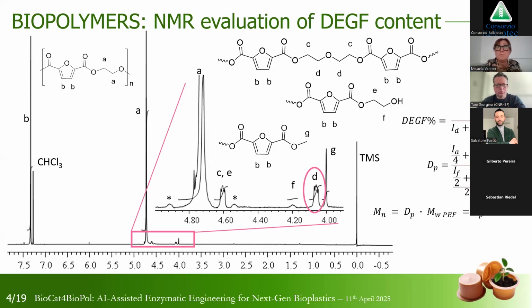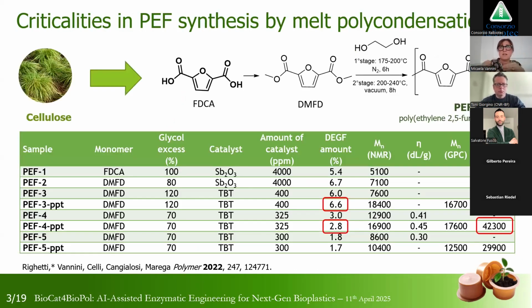For example, in the PET world, the presence of DEG lowers the melting temperature and glass transition temperature, slows down crystallization, and makes the polymer less thermally stable. So it's crucial to evaluate, but also to limit, the amount of DEGF.